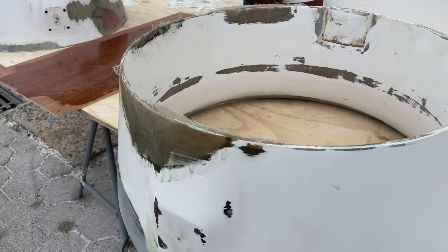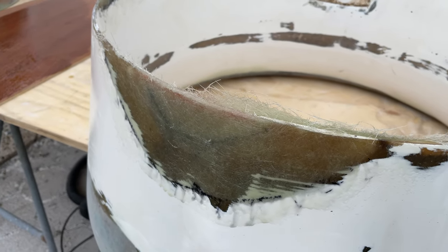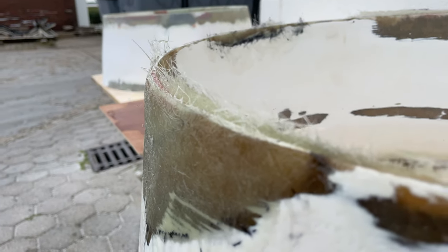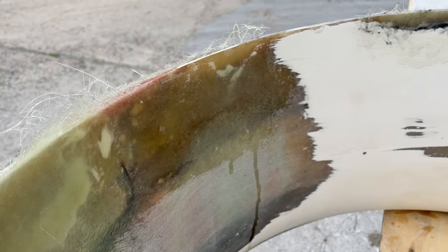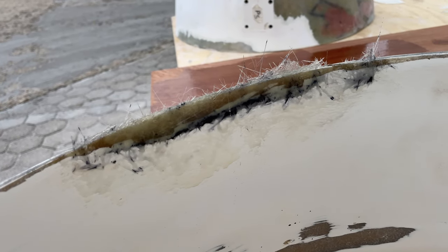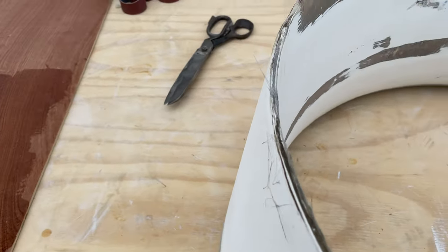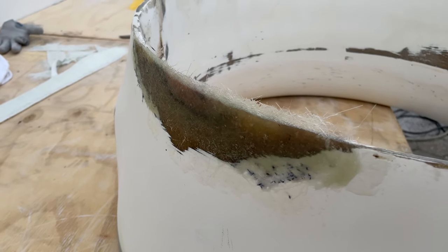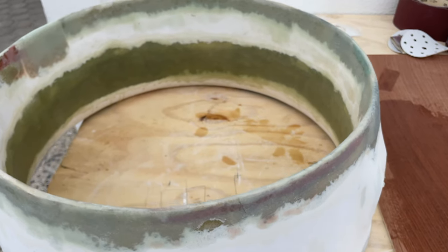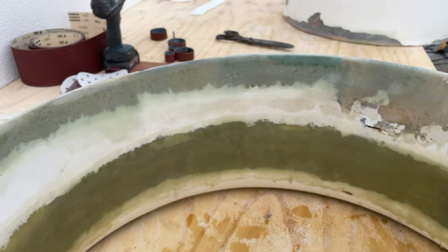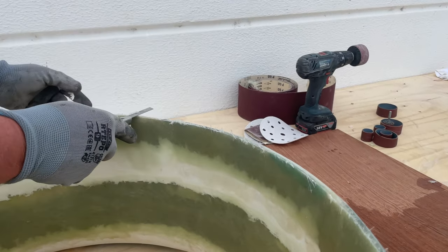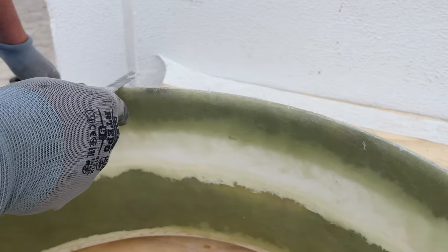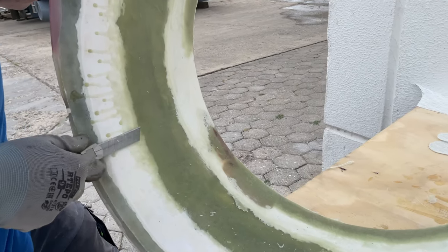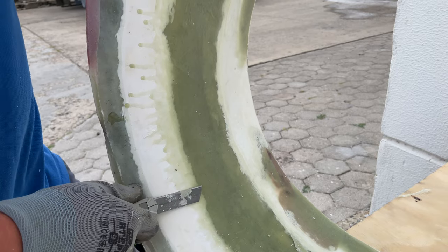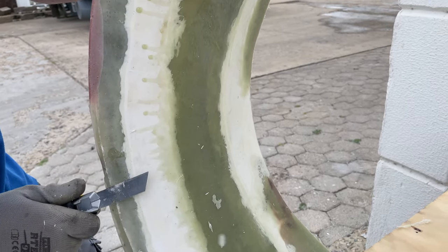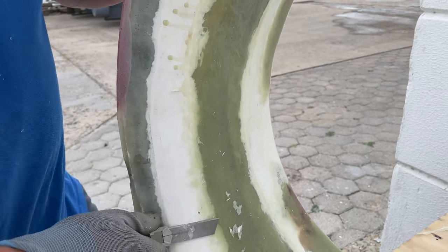With the new technique of not laminating around the corner, but rather laminating both sides individually, it was much easier to get close to the edge without having any air bubbles in there. At the same time, you always have some material left over on the edge that you need to get rid of afterwards. What I did in the first try was sanding it down with the orbital sander afterwards, but a nice little trick that one of the shipyard workers told me is just cut it off when it's not quite hardened yet. So not when it's fresh, but when it's almost finished with hardening, it's very easy to cut it off. The same thing obviously works for resin that ran down the side of your piece just as well. You cut it when it's almost finished hardening.